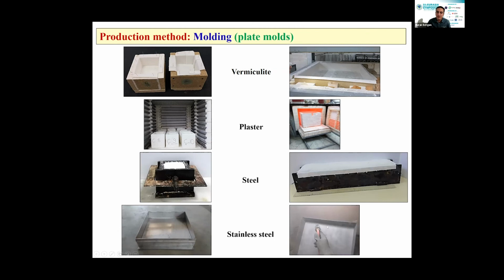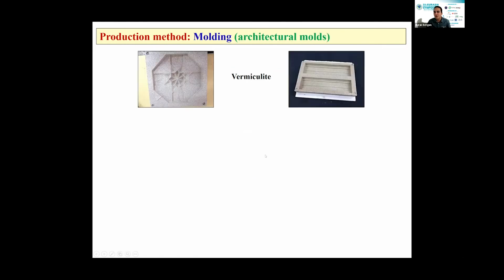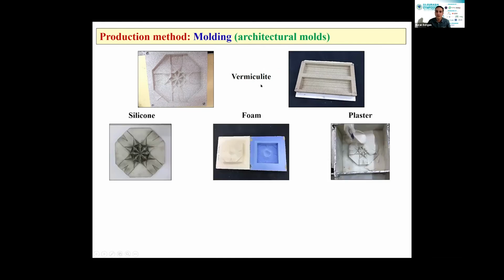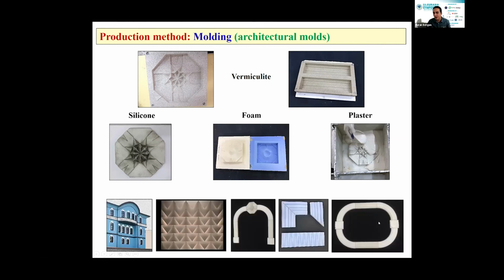Then sandblasting is applied on the stainless steel material, and then we use a paper type of material to easily take the specimens out of the molds. In the second stage, architectural molds, similarly we use vermiculite type molds at the beginning of this production stage. And then silicone, foam, and plaster type molds are used. And these are our final products.